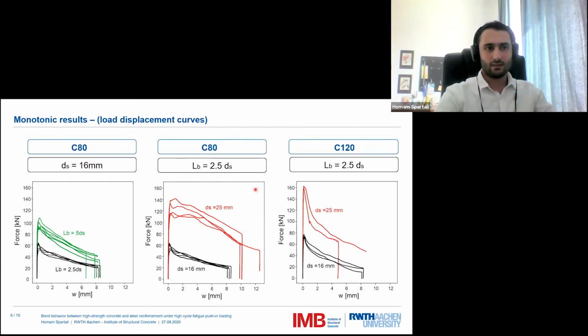And in this last figure, we see the result of the concrete C120 for the bond length 2.5 ds and the 2 different bar diameters. Now, by comparing the red curves in these 2 figures and the black curves, we see that by increasing the concrete strength, as expected, we also increase the reachable force or the bond strength.